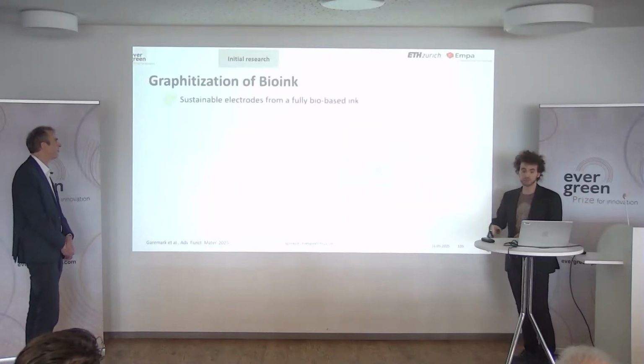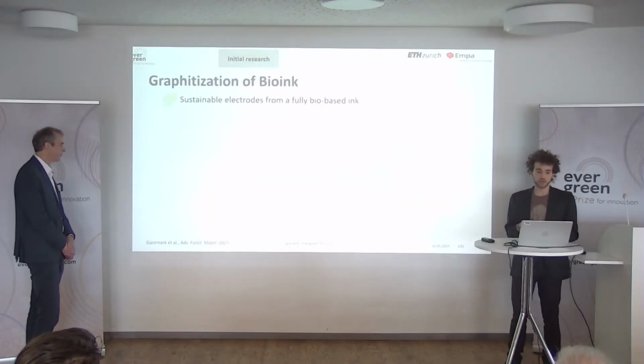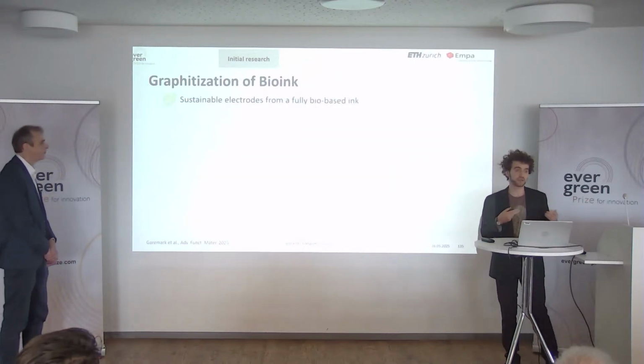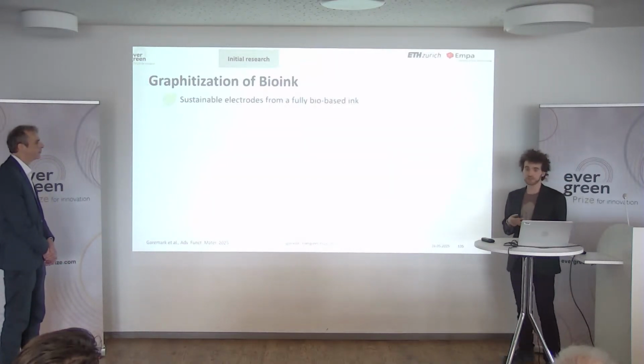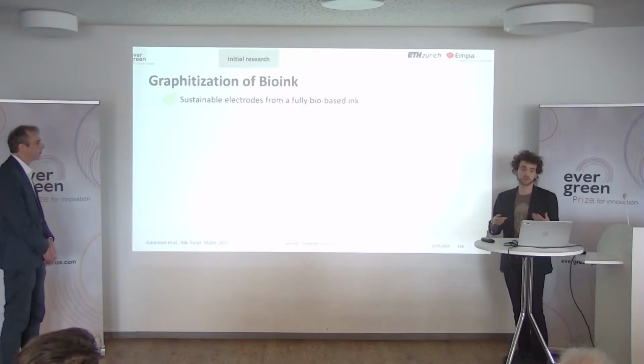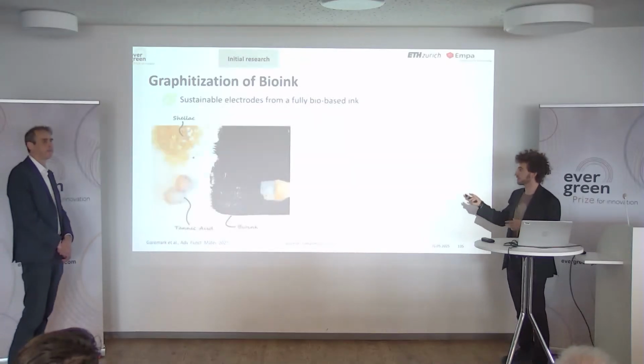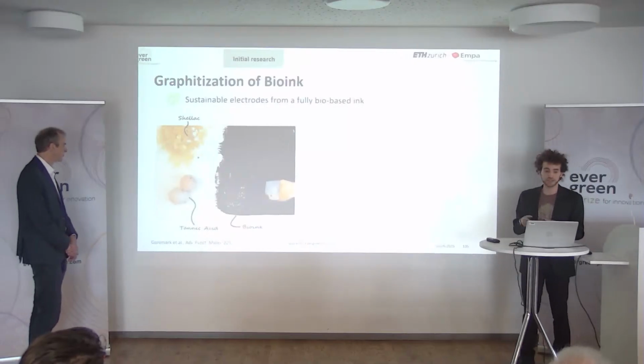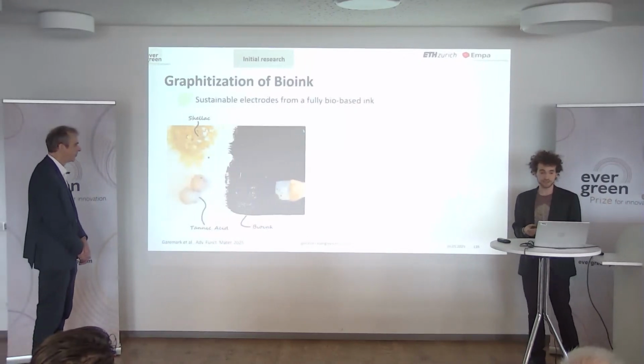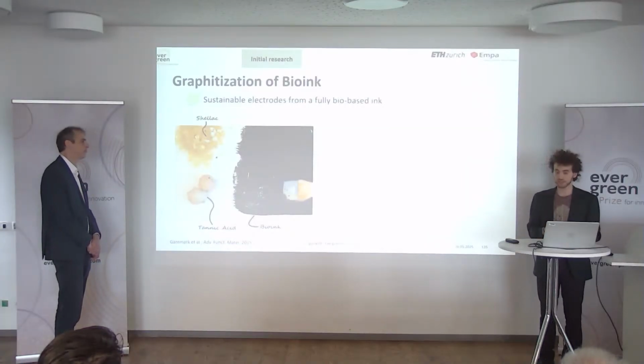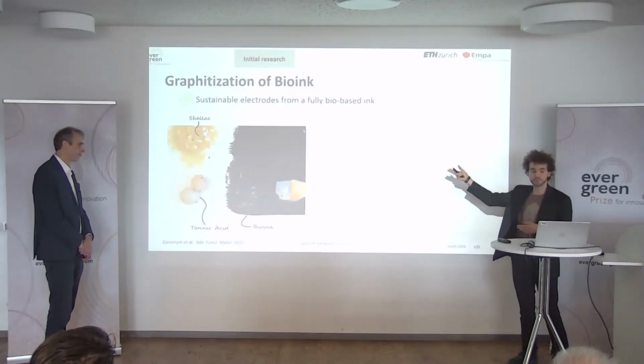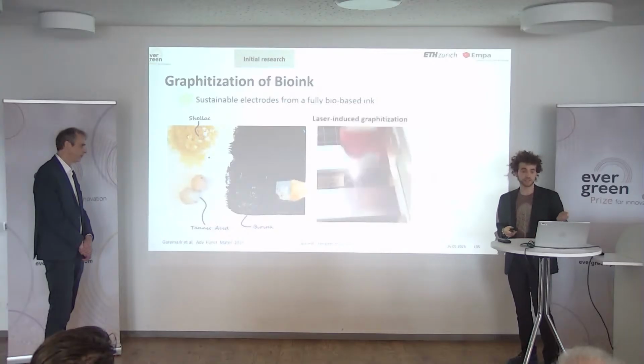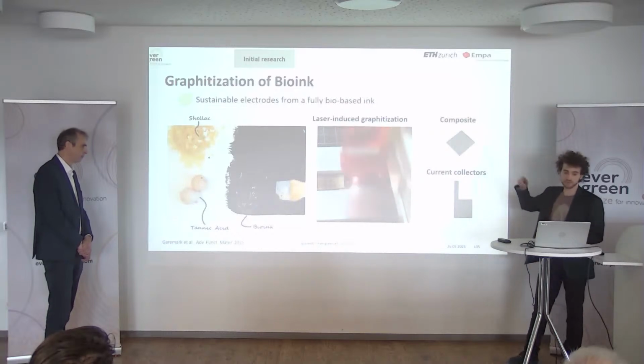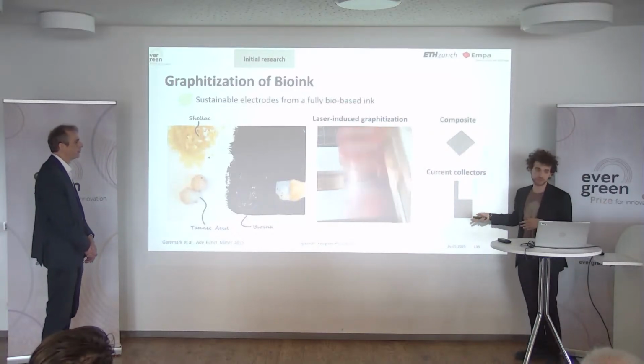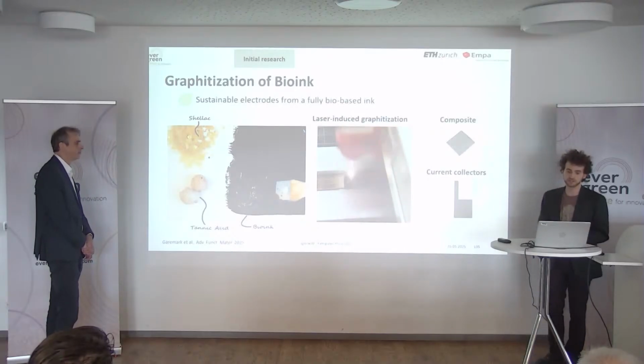So if we move further, when we go into this bio ink, we wanted to have sustainable electrodes, moving away from metals or silver, for example, that's very much used in the industry, as well as moving away from adhesives or fossil-based polymers. This we did by first using shellac, a resin excreted by bugs, and tannic acid, which we extracted from gallnuts, and we mixed it together with iron to create this very black bio ink that you can see. We then paint it, and graphitize it with a laser. Then we obtain our composite, which is conductive on the surface, and current collectors as well, made from wood with a conductive surface.